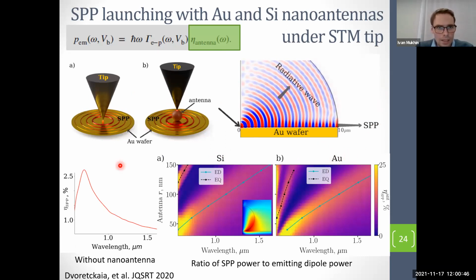Without the nano-antenna, the efficiency is just about a few percent, but when we consider the nano-antenna, this efficiency can be improved up to one order of magnitude. And what is more important, silicon material is as good as plasmonic material, as shown here. And what we have known is that the optical states of the nano-antenna govern the efficiency of light emission, or SPP launching. So this curve shows the position of the two branches, electrical dipole and electrical quadrupole, of the nano-antenna, and you can clearly see that for both types of antenna, optical resonances govern the efficiency of SPP launch.